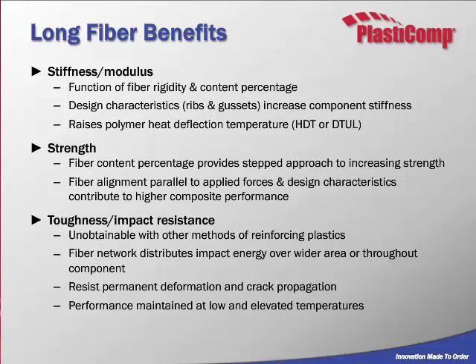Again, the advantage with the long fiber is that you can step this up to high levels. However, there is a point where you start to level off on strength as you add more and more filler. And as I mentioned, where long fiber earns its stripes is with the impact resistance. So the longer you can keep your fiber length in the final part, the higher your toughness will become. And what's interesting with long fiber materials is your impact resistance is the same at room temperature as at -40, and to certain high temperature levels as well.